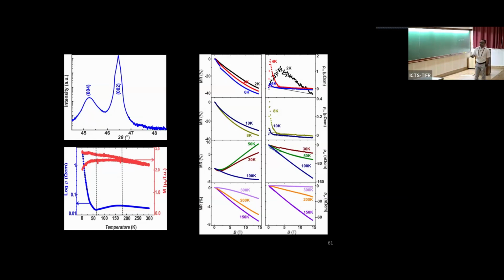So this is happening exactly at this position, this negative to positive magnetoresistance transformation. And again, at higher temperature, there is a transformation from positive to negative magnetoresistance. And you see, this is the Hall data. At very low temperature, we tried to fit with the anomalous Hall formula, but it doesn't fit, and it gives rise to some additional Hall signal, which seems to us like a topological Hall, but we are not sure about the origin of this extra Hall term.